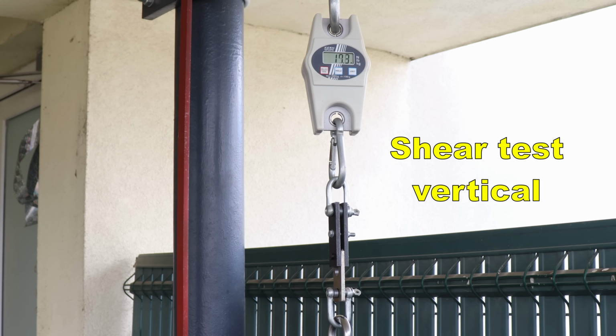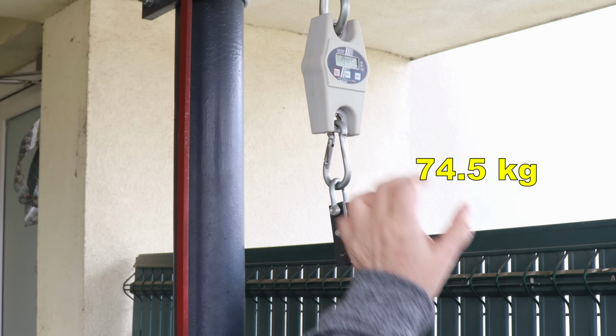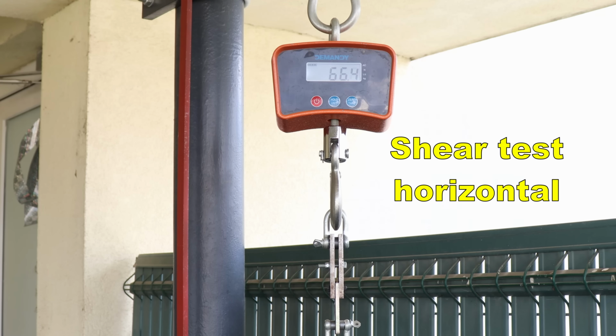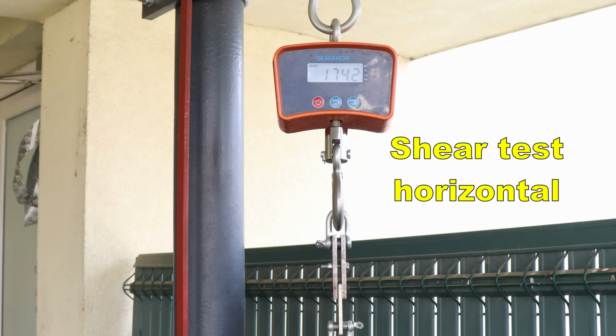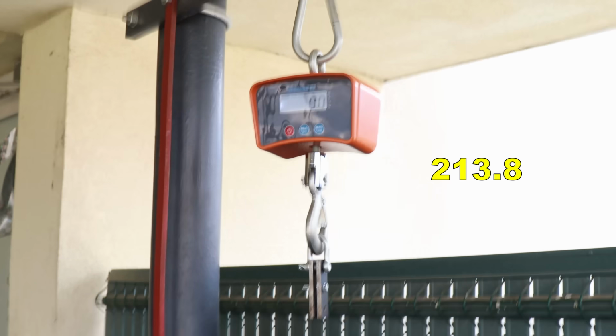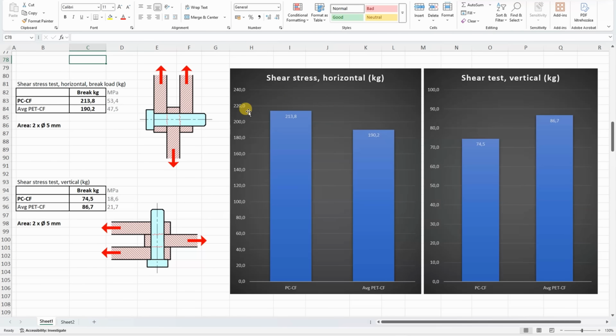Shear test, starting with vertically printed, horizontally printed with stronger crane scale, printed in horizontal position. Fibers always help here a lot, and we can see a small advantage compared to the average PET-CF, and basically only some special nylons are stronger than this PCCF. Printed in vertical position, a small advantage on the PET-CF side, but this is a good value too from PCCF.